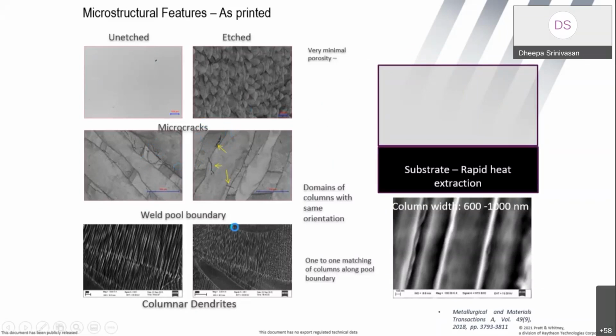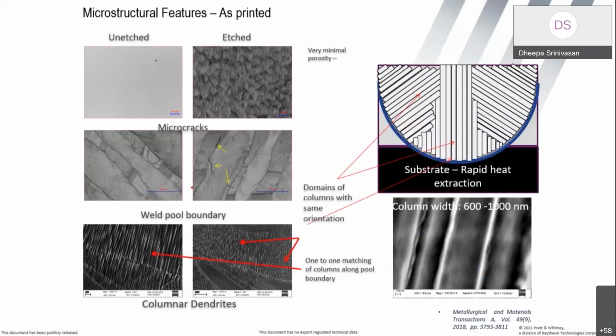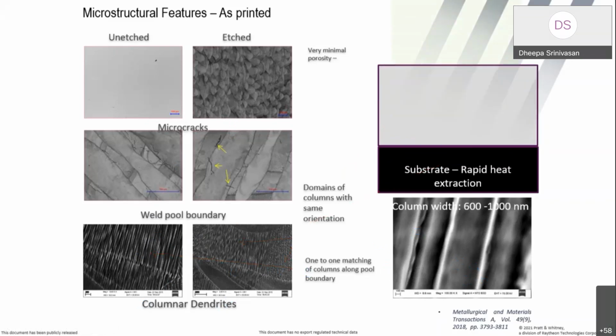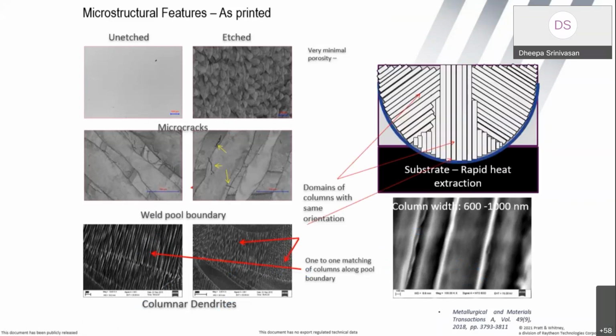And then if I blow up the weld pool boundary, what you can see here is fine athermal HCP plates, which can only be discerned in the TEM, but nevertheless, we were able to see it in the SEM. And if I look at the heat extraction, this is supposed to be a video, but it's okay. So you can see that there are domains within one weld pool. As you look here, there are domains of similar orientation out here. And sometimes this translates from one weld pool to the other.